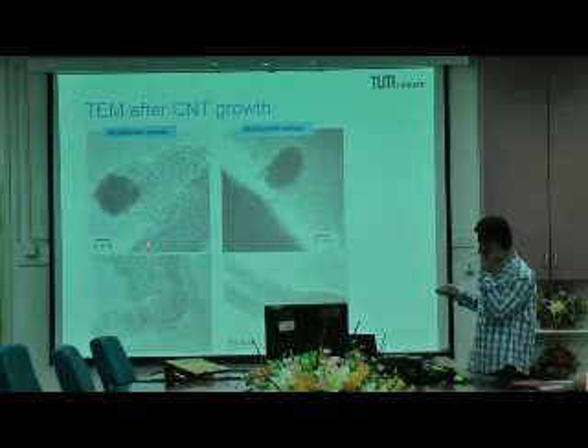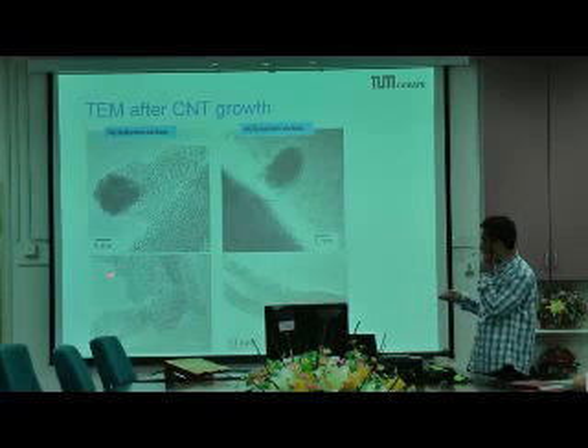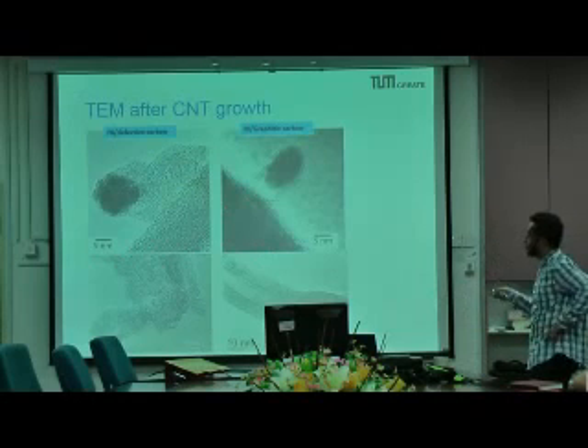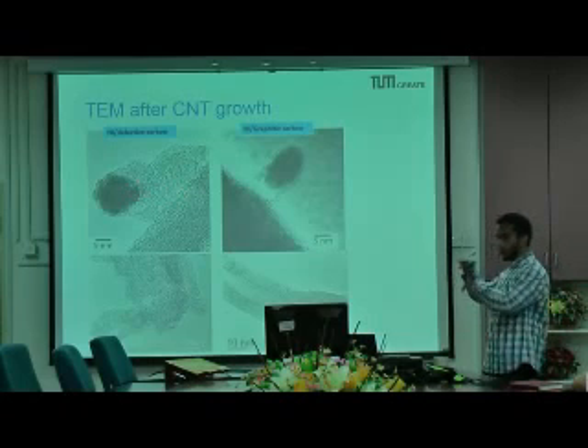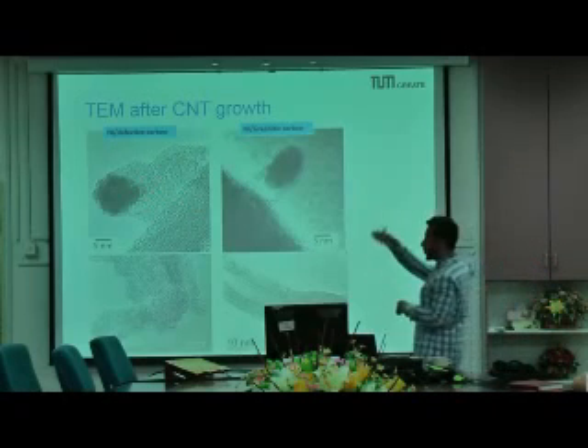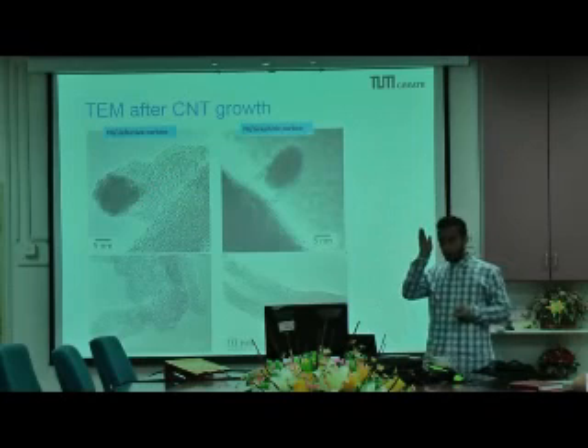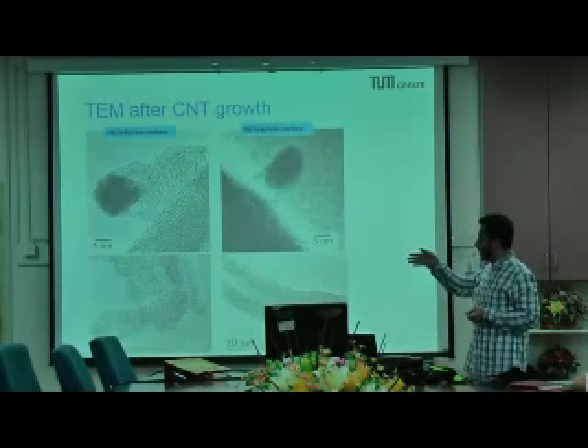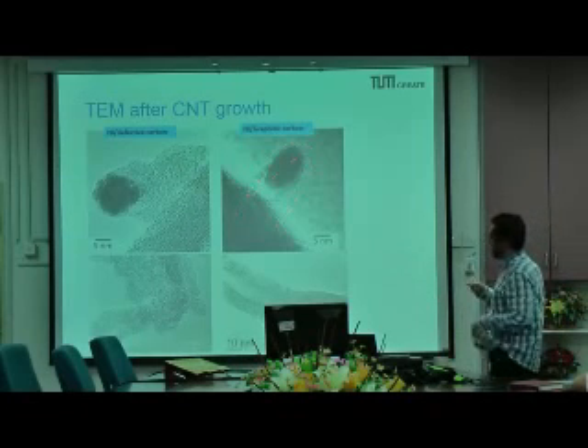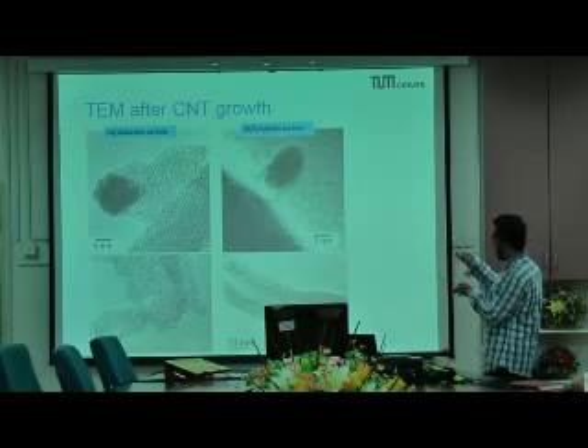The results when you deposit the nickel nanoparticles onto two different surfaces, defect-rich and graphite-rich, are, as you see, quite significant. The nanofibers or nanotubes that grow from a defective carbon have a very unorganized graphene structure. It doesn't have a specific orientation. This grows everywhere. If you notice here, the straight lines represent the graphene ring branches that are in projection with the electron beam in the TEM microscope. Whereas for the graphitic carbon, you see here that the growth is very oriented. It has one direction for the graphene orientation from the nanotube.